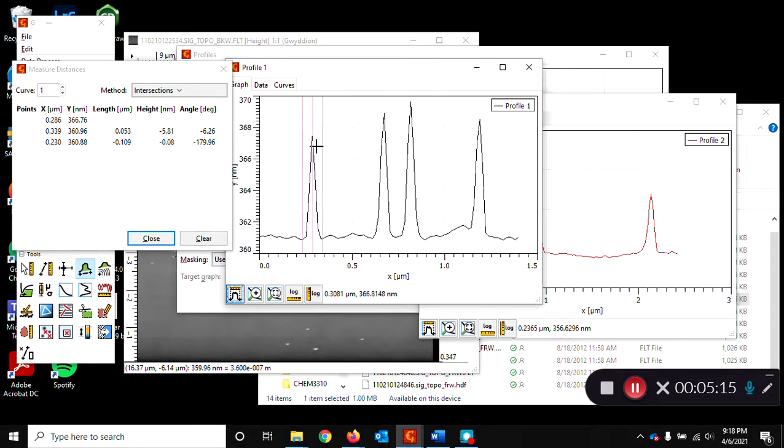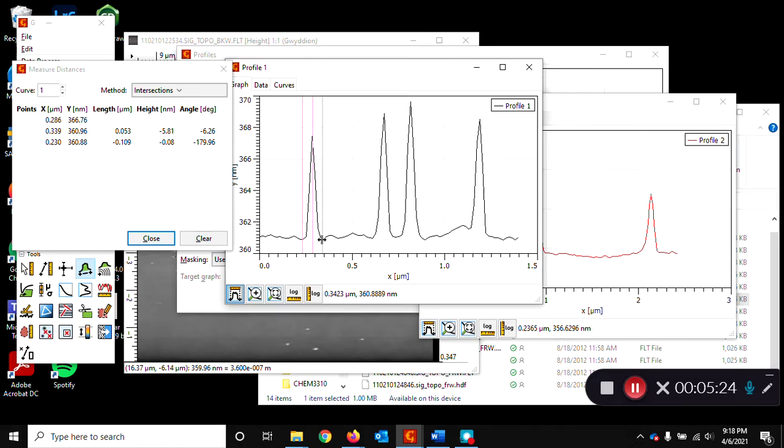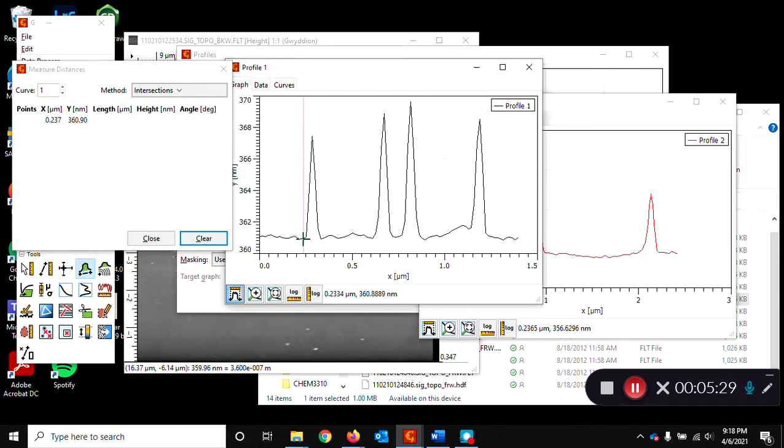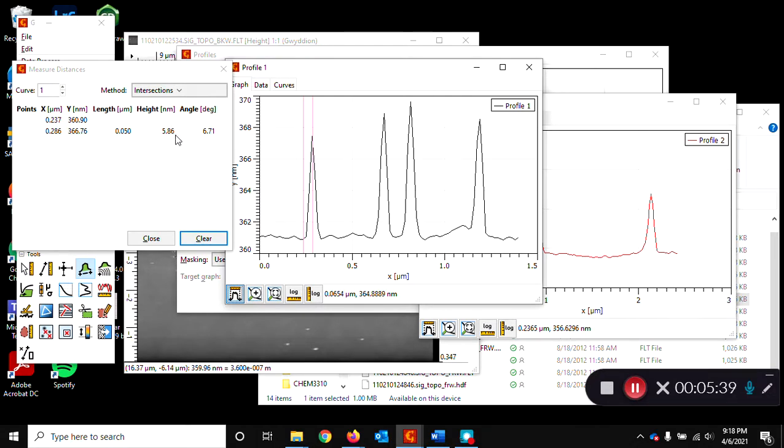Here's the height, oh, since I started at the top of the peak, then it goes from negative from the top down to this peak, negative 5.8 nanometers. Maybe we want to actually do this differently. Let's start at the base of the peak and then measure the top of the peak. And so that gives us the height, 5.86 nanometers, and that should be the diameter of our nanoparticle.